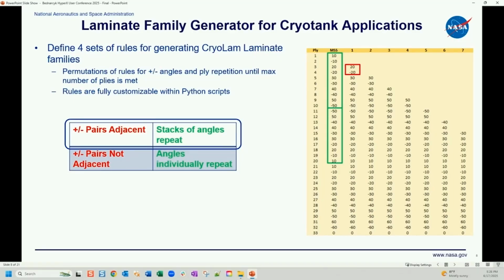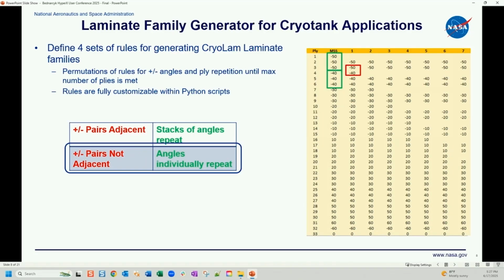So as I mentioned, we have a laminate family generator. We defined 4 sets of rules for generating these cryo laminate families. Basically, we have pairs of those angles being adjacent, and then repeating stacks of angles, and that's kind of shown here. And then we have another condition that plus-minus pairs are not adjacent, you can see. So we just have all the, can't quite read that, is that plus or minus 50? That's minus 50. So all the minus 50s are next to each other, then all the minus 40s. And then we also fully permuted this. So there's 4 sets of rules.